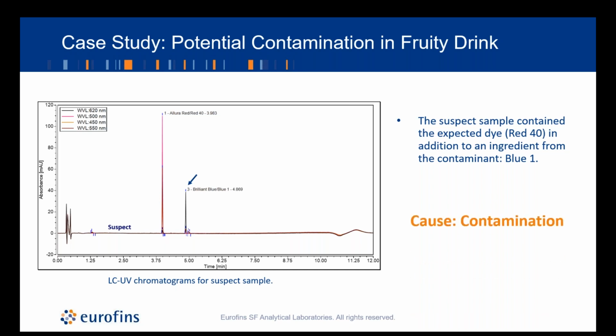And so the conclusion in this case was that we confirmed that contamination had indeed occurred, and based on our LC-UV data and also our GC-MS data, this suggested that they may have had contamination from a blue-colored isopropyl alcohol-based cleaner or disinfectant agent.